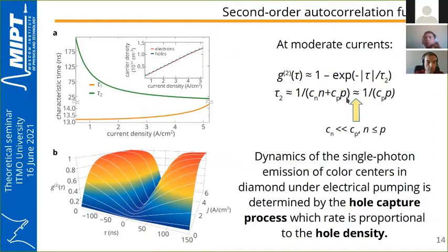And in this case, we should remember that the electron is captured by the neutral NV center, but the hole is captured by the negatively charged, attractive NV minus center. And therefore, the hole capture constant should be much higher than the electron capture constant.